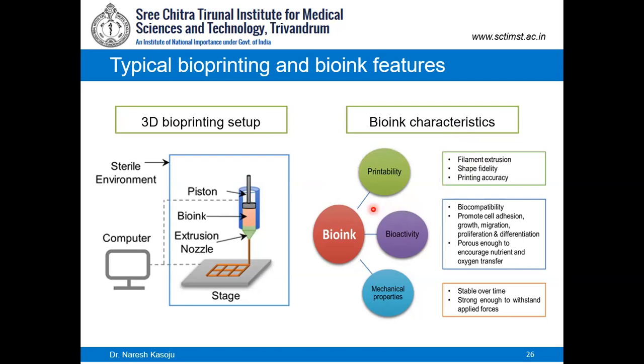But what is more critical and the deciding factor in the field of 3D bioprinting is the bio ink. It needs to tick a lot of boxes, starting from printability and looking into the bioactivity and the mechanical properties. One needs to look at the way the filament is being extruded. One needs to control the shape fidelity, whether it is retaining its shape or simply collapsing after printing. What is the kind of printing accuracy that is being achieved with that formulation, and whether the formulation is compatible, whether it is safe for the cells, whether it has any positive effect on cell adhesion, growth, migration, proliferation, and whether the porosity of your bio ink or the 3D printed construct is good enough for oxygen transfer or nutrient transfer. Otherwise, again, you will have the same issue of necrotic core, just like in your conventional system.